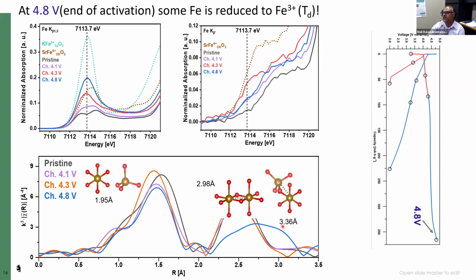And this clearly, in conjunction with what we see from the X-ray absorption, shows that surprisingly but interestingly, the iron actually oxidizes, the oxidized iron reduces to Fe3 plus and migrates, a part of the iron migrates to tetrahedral sites. This, we believe, is because this material actually loses oxygen, and the loss of oxygen in the material is compensated partly by the reduction of transition metal.